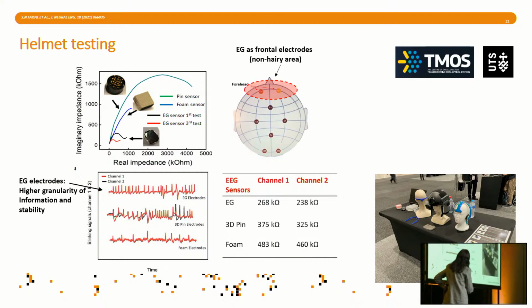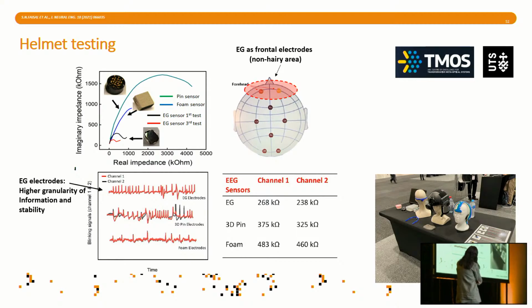And here you can, even without knowing much about what this all means, see two sensors, a signal on the frontal cortex. These are the graphene sensors, these are the pin electrodes, and these are the foam electrodes, the commercial ones that you see here. You can see that the quality of the signal picked up by the graphene sensors is definitely much more valuable than, well, the foam sensor would be the worst, as you can see here. And impedance is a big part of the story.